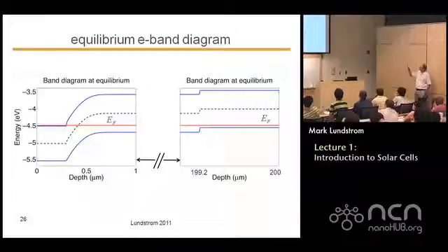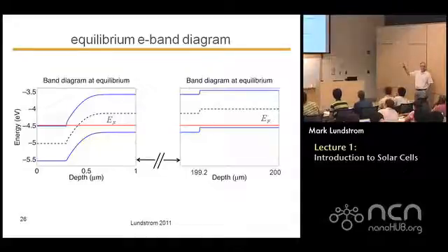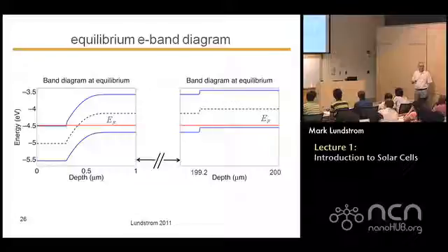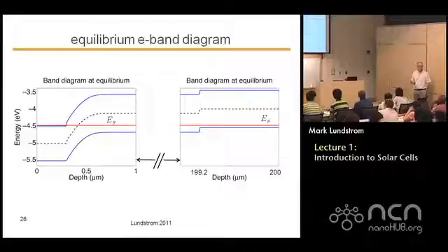And this is something that we'll talk about in my lecture tomorrow. You can see an energy barrier there. We're going to insert excess electrons in the conduction band, and they have to hop over that energy barrier if they are going to get to the contact. That's designed to keep them from getting to the contact, because the contact is a defect where they recombine. It's called a minority carrier mirror.